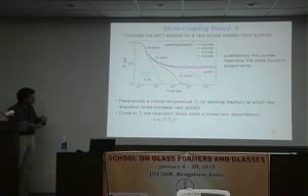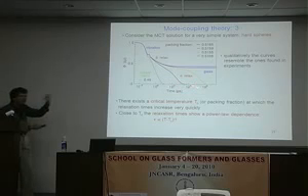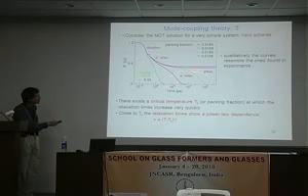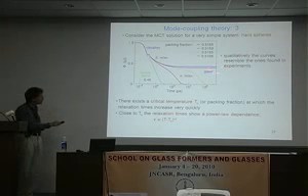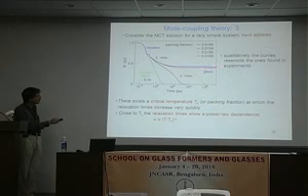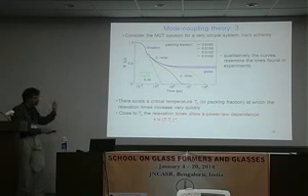In order to give you an idea of what's happening, this is a hard-sphere system within this mode coupling approximation, for different packing fractions. You see qualitatively this does indeed look like the time correlation functions that we look at. If you are inside this glass here, then nothing relaxes anymore. There is a critical temperature Tc, a critical coupling, below which the system does not relax anymore. There you are in the glass state. And the alpha relaxation time is predicted to increase with a power law.